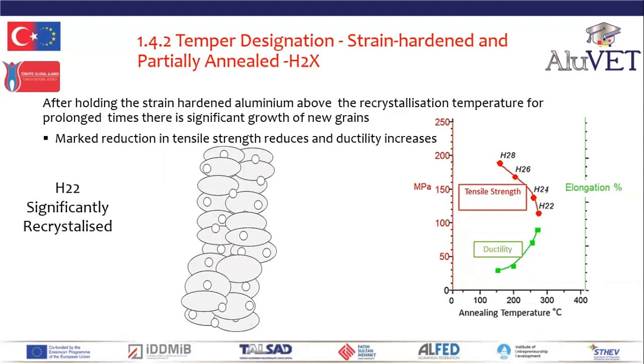As we continue to heat for very long times above the recrystallization temperature, the rate of recrystallization, that is the growth of the new grains, becomes significant. The significant growth in new grains results in the H22 condition, partially annealed, quarter hard state, with a large reduction in strength but greatly increased ductility. If we're intending to heavily manipulate, bend, or form the aluminium, then we need to use it in the H24 or H22 tempers.